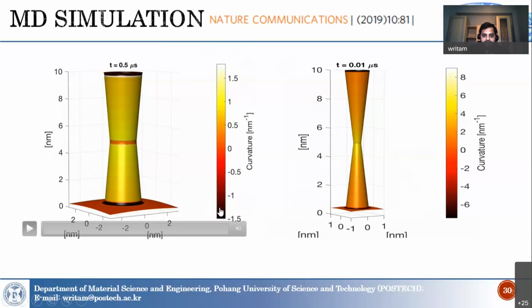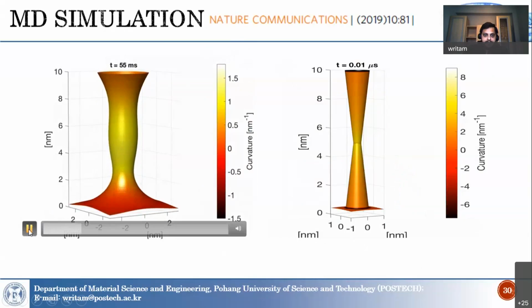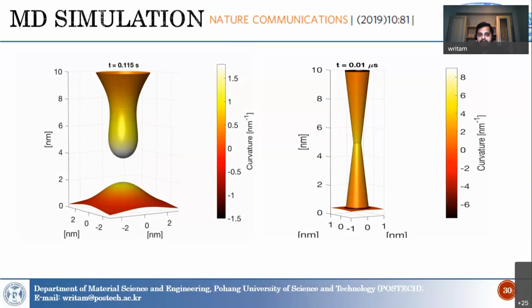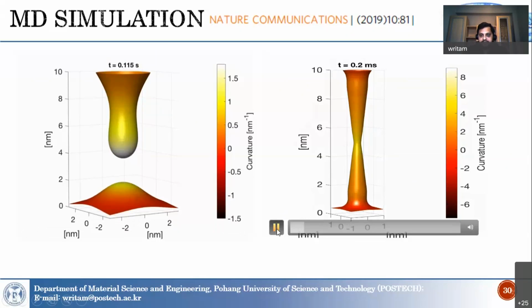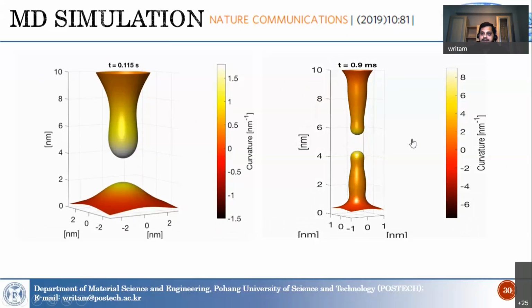Now, if you see here, if you have a thick filament, please concentrate on the time. You can see the time to break the filament in the simulated image. When you have a thick filament, it looks like almost 0.1 second, or it can be even larger, depending on the thickness of the filament. Now if you have a thin filament, a thin junction, it's just 0.9 millisecond, or it can be even lower, again depending on the thickness.